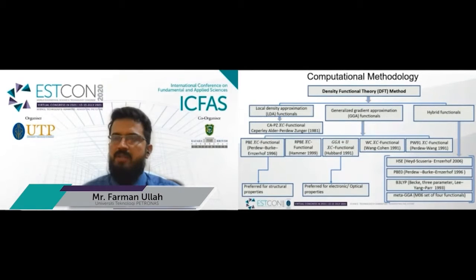Computational methodology. Density functional theory calculation basically depends upon three exchange correlational functionals that include the local density approximation, LDA functional, the generalized gradient approximation, GGA functional, and hybrid functional. For the current research work, we introduced GGA functionals to the computationally designed model. For the calculation of structural properties, we employed the PBE exchange correlational functional, and for electronic and optical properties we employed the GGA plus U Hubbard modified exchange correlational functional.